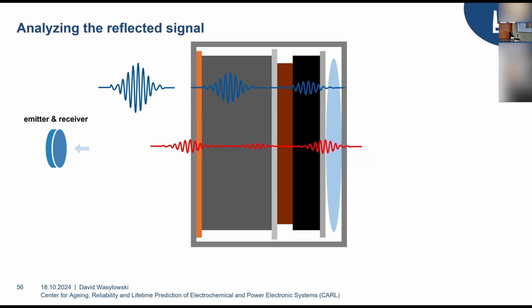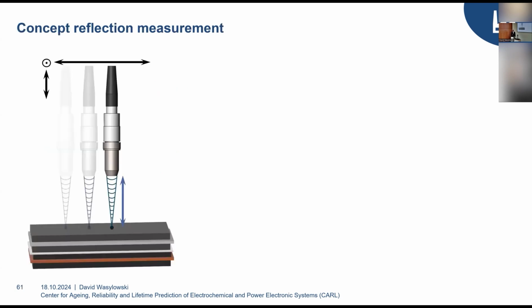And if we now have another look at this measurement from this reflection point of view, we would first emit an ultrasound wave, and because of the limited speed of sound, we would have to wait a few microseconds where we get our first reflection here at the surface. So this is where we have the surface information, and when we wait a few more microseconds, we get this deposit information, and then after a few more microseconds, this gas information. And if we now just connect this time domain to the depth domain, we are in fact just able to assign reflections that are happening within a point in time to a depth within the battery cell. So this is what we did in our latest work.